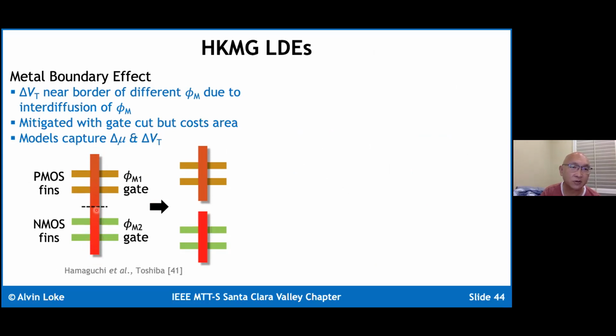But it turns out that when you're building such a structure, there is going to be interdiffusion of work function metal between the two, cross-contamination of the work function metal. And when you've got cross-contamination of the work function metal, it also means you have cross-contamination in VT. And so if you've got devices, transistors or fins that are very close to this metal boundary, you're going to end up with VT shifts.